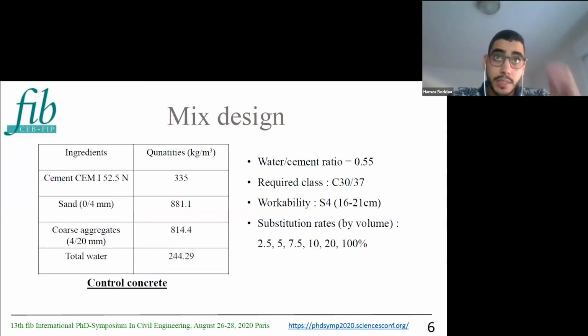So the control concrete in this study is a concrete of C30 class with a good workability as far as slump class, using a water to cement ratio of 0.55. This study is carried out on 7 concretes, one control concrete and 6 concretes based on shells. The volume substitution rates used in this study are 2.5, 5, 7.5, 10, 20, and 100%.